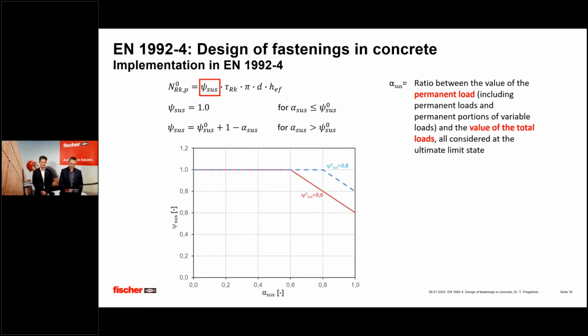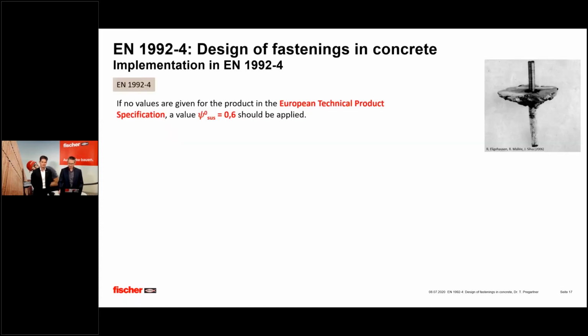If you draw now the equation of psi sus in a diagram, then you get this picture. Psi sus is on the y-axis, alpha sus is on the x-axis, and you see that psi sus stays 1.0 until the value alpha sus reaches psi null sustained. And then you start decreasing your characteristic resistance until the full reduction factor of 0.6, which is the red line here, once you reach 100% creep load compared to the sum of the total loads. Now, where do you get this factor of psi null sus from?